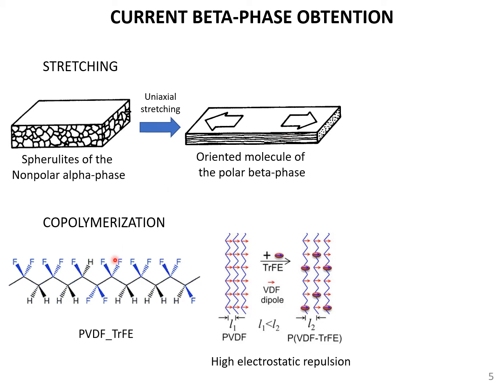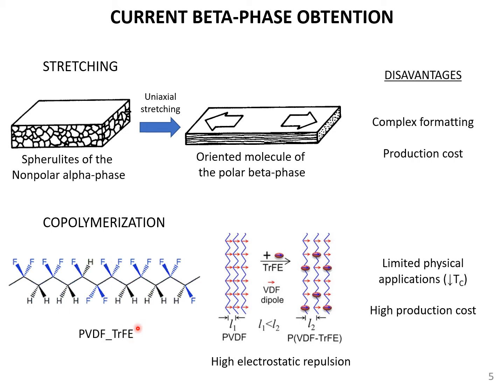Or you can carry out a copolymerization, meaning that you introduce a common monomer inside the backbone of the PVDF, like TRFE. Of course, this methodology has some drawbacks, like complex formatting and also the fact that you have to increase the production cost based on the stretching approach, or in the case of copolymerization, you can have some physical limitation, particularly the Curie temperature decreasing with the content of the comonomer inside the PVDF chain.